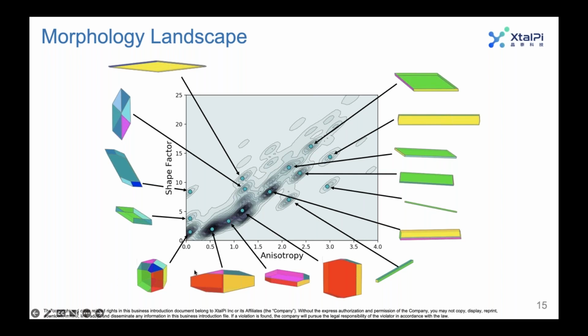So you go from very spherical morphologies in this bottom left corner to needle-like and plate-like morphologies as you go up and across, respectively. And the way we obtain this is we take those morphologically important faces and we vary the surface areas that you could potentially obtain. That allows you to basically explore the landscape of the possible morphologies by sampling different surface areas for those morphologically important faces. And the two descriptors allow us to calculate them.